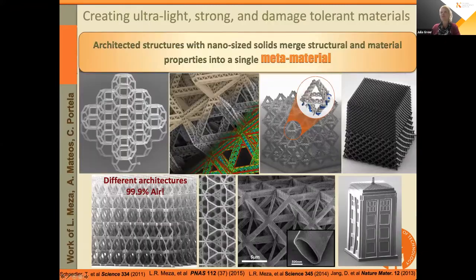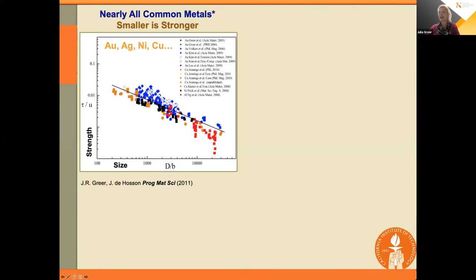what we and several other groups showed is that, again, on the log-log plot, there's this power law strengthening of all common metals in their single crystalline form. So what that tells you is that if you take something very malleable, like a gold earring, for example, and reduce its dimensions to about 200 nanometers, it becomes as strong as steel.